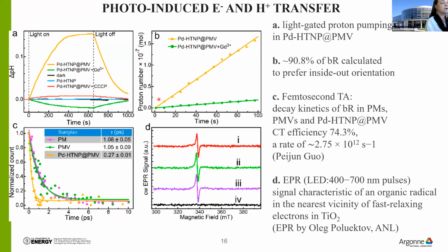So it allowed us, using this gadolinium blocker, to calculate overall preference of proton transfer, and we discovered over 90% of purple membranes are oriented the way that protons can go inside of the hollow nanoparticles. So then we switched to the study of charge transfer between biotic and abiotic parts of our architectures.